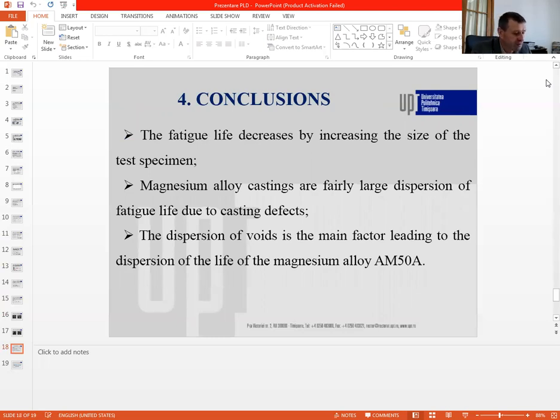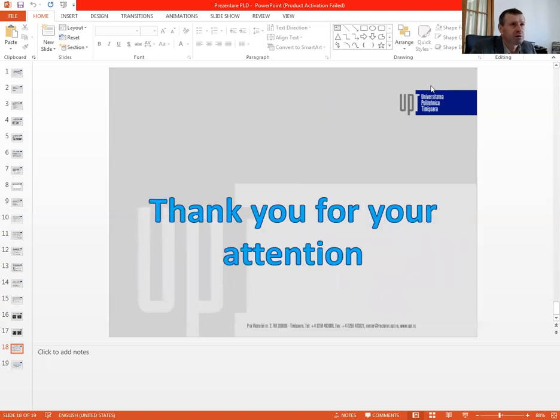Conclusion: the fatigue life decreases as the size of the test specimen increases. Magnesium alloy castings show a fairly large dispersion of fatigue life due to casting defects. The dispersion of voids is the main factor leading to the dispersion of the life of magnesium alloy. Thank you for your attention.